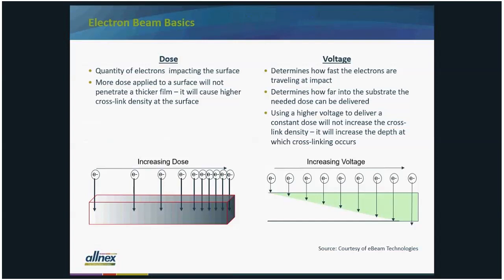One of the nice things about electron beam is that you can easily control both the cure and depth of cure independent of each other. The applicator, or the person running the equipment, can control both dose and voltage. The dose refers to the quantity of electrons impacting the surface, and that again goes to cure speed and cross-link density. Higher dose will not penetrate any deeper, but it will cause higher cross-link density at the surface of the film and higher cure speed.